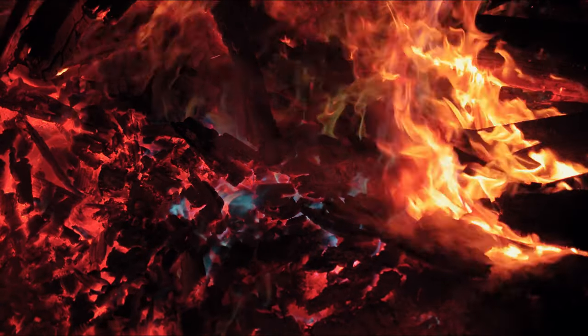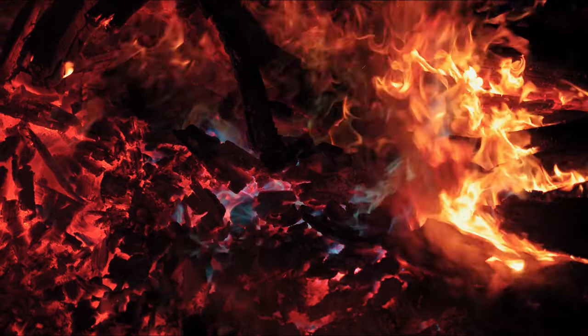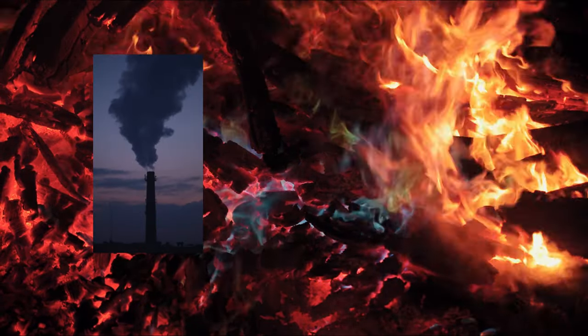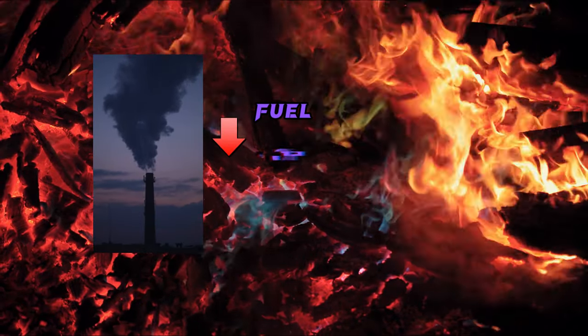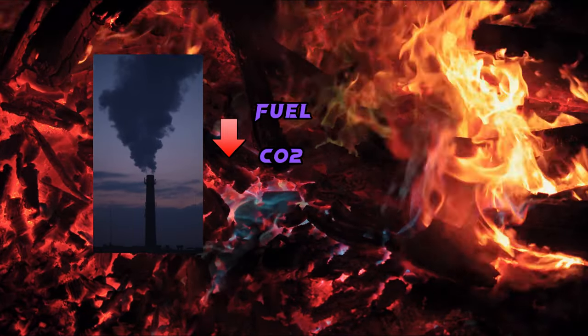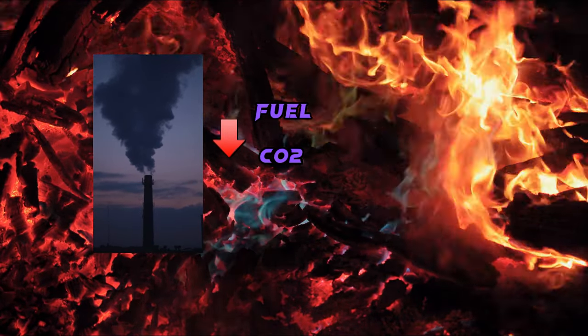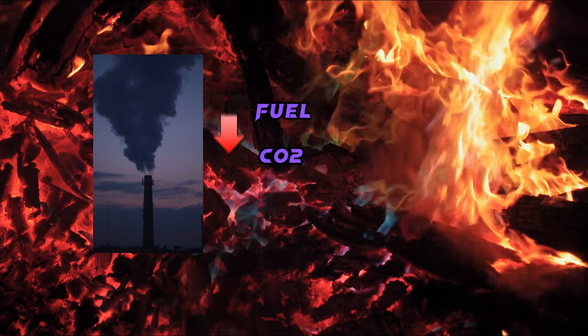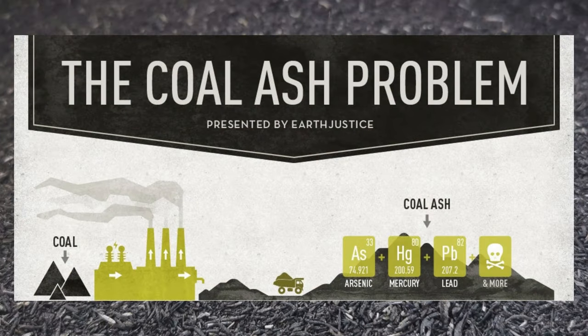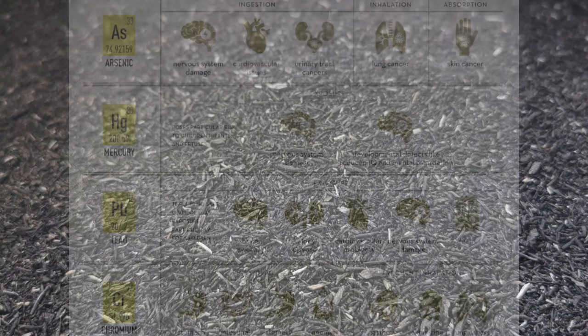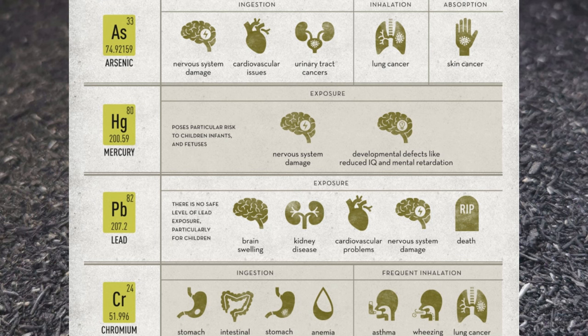Rice husk ash bricks have the added benefit of not requiring firing, which reduces the cost of fuel as well as carbon emission when compared to fired clay bricks, and is an economically sound choice that also equates to environmental benefits. The fact that rice husk ash is less toxic than fly ash, as fly ash contains many heavy metals, can be a competitive advantage for using rice husk ash over coal fly ash in making brick.